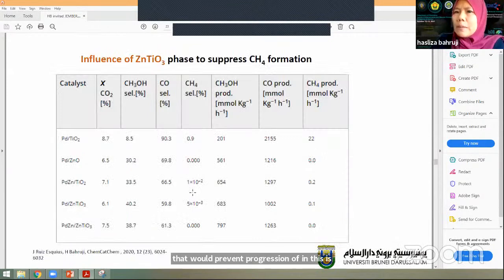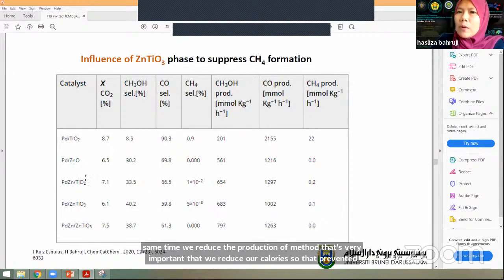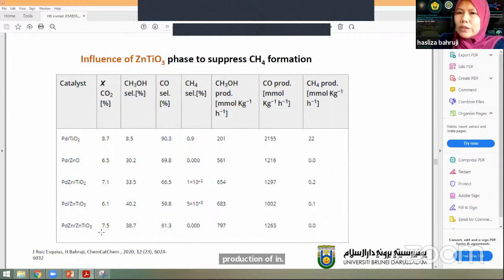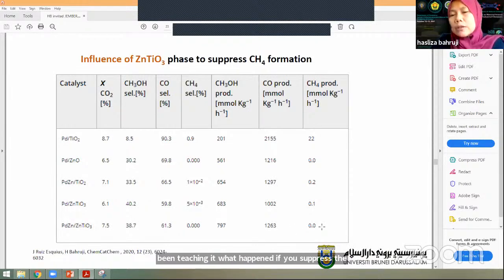This is another example, where we can transform our catalyst support from titania to zinc titanate. By having zinc titanate, we suppress the methane production altogether. This is another indication that if a certain type of experiment requires us not to have any methane, we have to transform our titania support into a zinc titanate support that can completely remove methane from the reaction.